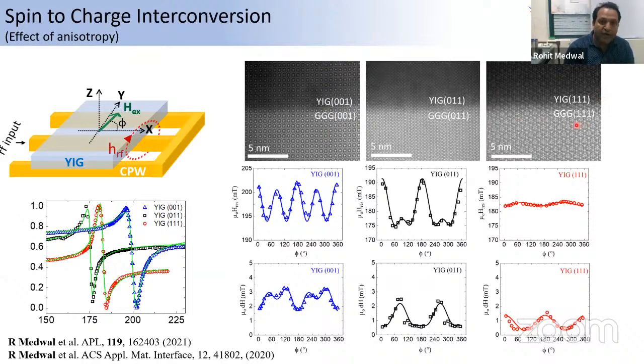And we took quite a long time to grow them in a very perfect manner, so that they really follow the cubic anisotropy, the uniaxial anisotropy, and the non-cubic anisotropy in the 111. We can clearly see here a 4-fold symmetry which dominates the cubic anisotropy. In the 011, we have a dominant uniaxial anisotropy with a small amount of cubic anisotropy, and in the 111 there is no significant cubic anisotropy in the system. We successfully demonstrated this in our APL paper and then our ACS Applied Materials and Interfaces paper, where we clearly show that we can control these anisotropies and various parameters in this system.